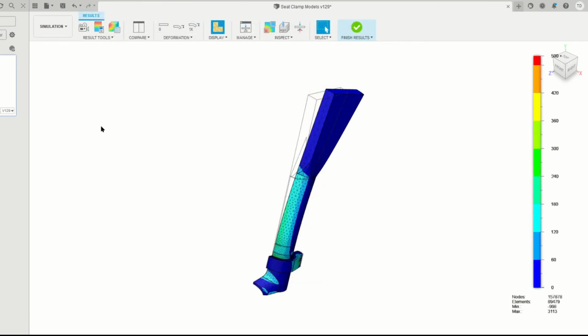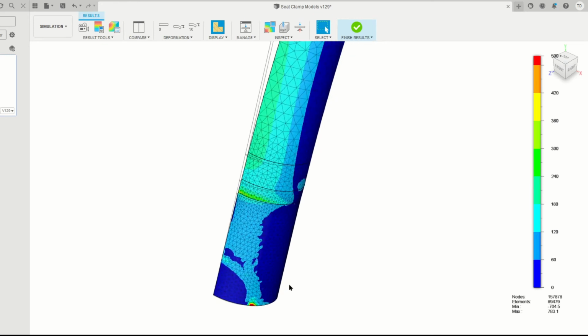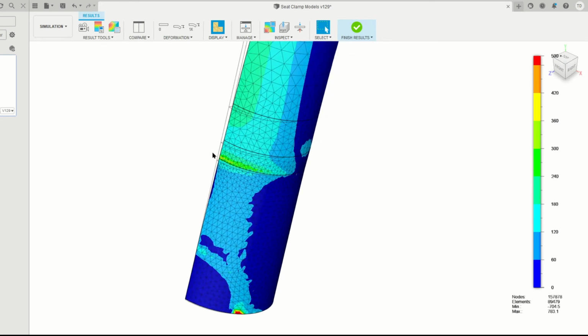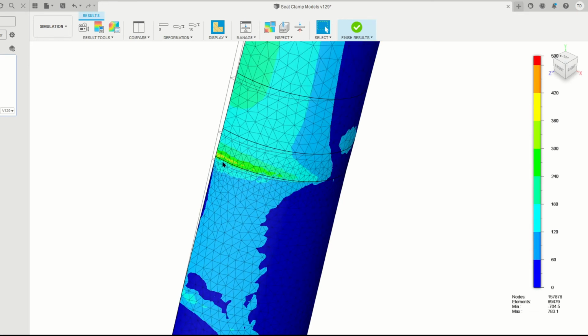So if we look at the maximum stress that occurs in the seat pin at the top of the seat tube, we're getting about 350 newtons per millimeter squared, which is lower than the assumed minimum strength of about 500 newtons per millimeter squared for the carbon fibre composite. So the seat pin, without the glass fibre layer on the inside, is still strong enough. So why put the glass fibre there? After all, it's just adding cost, not saving it.